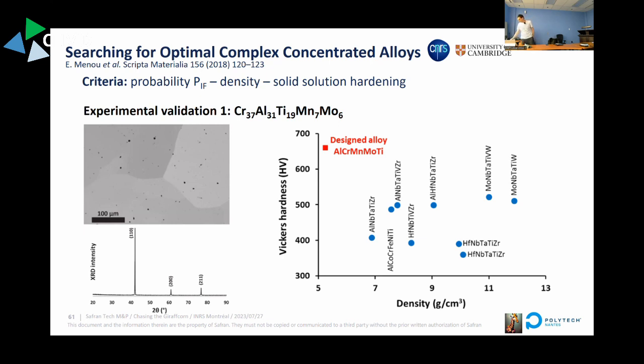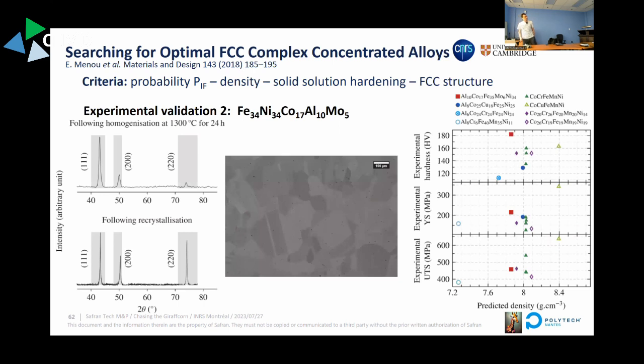And the other one is approximately the same, with no other contribution to hardening than that of the solid solution, which is that there's no grain boundary, certainly, or very little. There's no precipitate. There's just pure matrix deformation. And so our alloy is there. It's the red square, and same as before, be it in terms of hardness or UTS, YS is compression testing. We had something whose specific properties were better than that of comparable alloys.